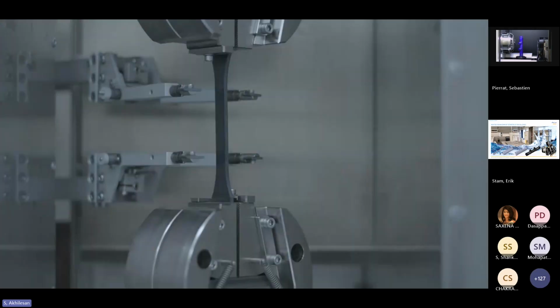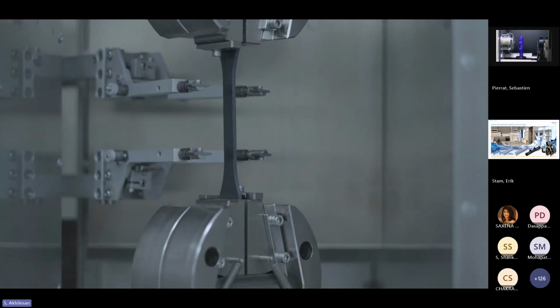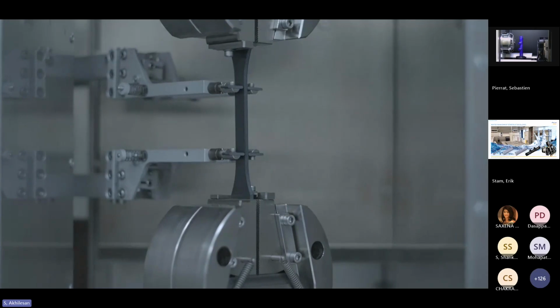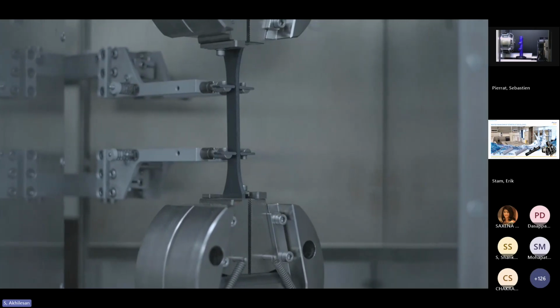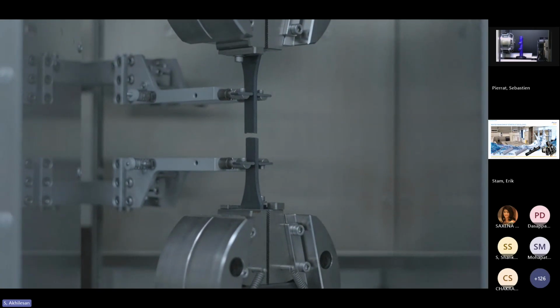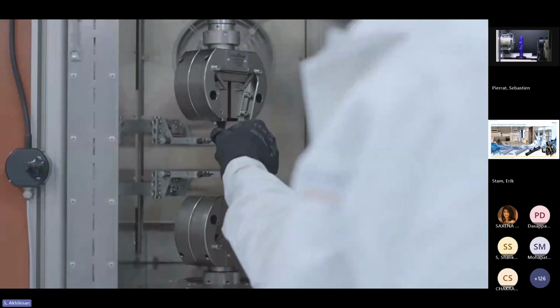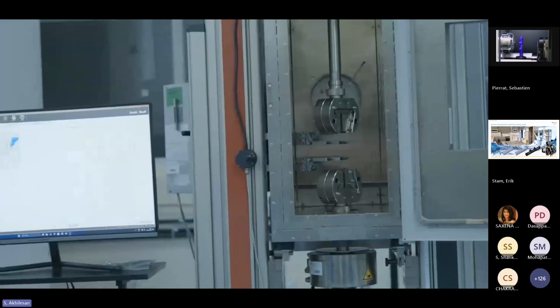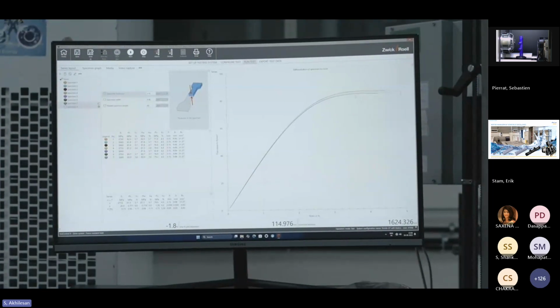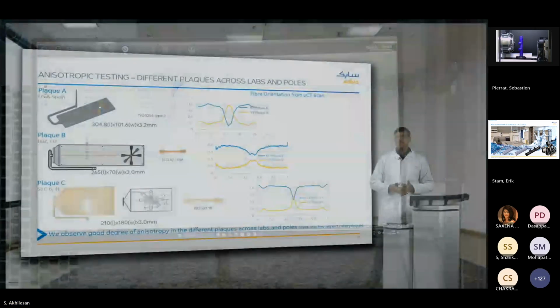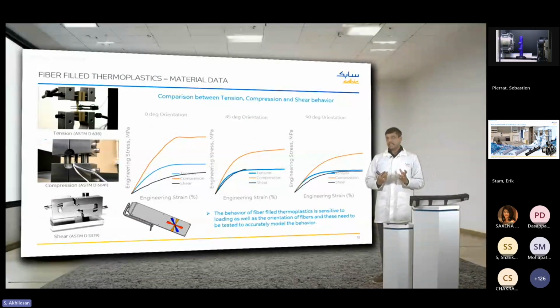Here we can see us carrying out a tensile test on our UTM, and typically we make sure that we have the extension in the gauge length captured using an extensometer all the way till failure. And not only the stress versus strain, we also try to capture additional information such as the crosshead movement and the reaction forces experienced by the load cell. With this, let us take a look at, apart from tensile testing, what else do we need to characterize in order to fully understand the behavior of fiber-filled thermoplastics.